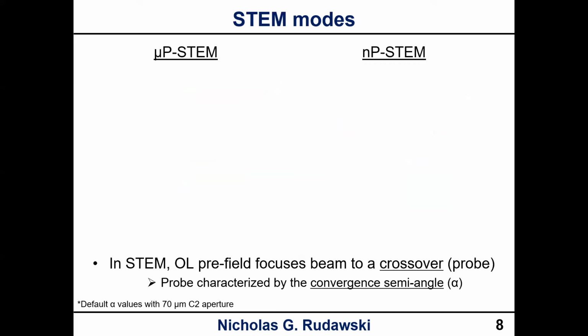Okay, so now just because we have the additional crossover before the objective lens pre-field in microprobe mode, that doesn't mean that we can't still focus the probe to a point. We could still do that in microprobe mode as well as nanoprobe mode. The difference here though is that because we have that mini condenser lens optically on, our convergence angles for the probe are much smaller in microprobe than in nanoprobe.